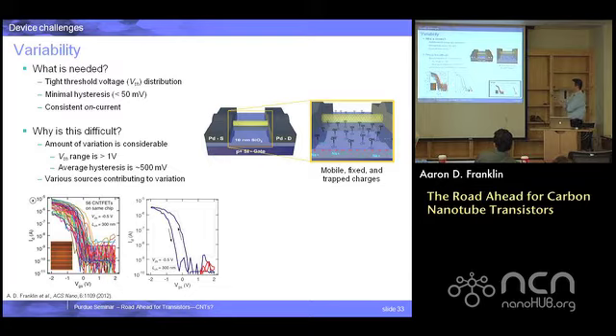Variability, what I mean is if you're building devices out of carbon nanotubes, and you have a band gap that's pretty consistent. Let's say you have diameters that are close to each other. So your band gap's not changing a lot. What would the device characteristics look like? Well, this is only 56 of them on a chip. And you can see, and this is over a 4 volt range, there's a spread of over a volt in the threshold voltage for these devices. Just having the same gate dielectric, the same device structure on the same chip, that's a lot of variation.